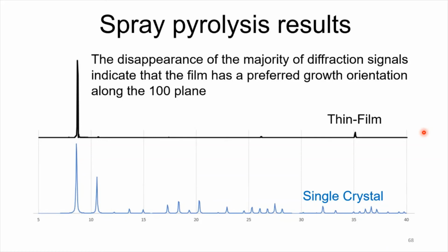As you can see, or what you cannot see, is the rest of the peaks. You can barely see some signals in there, and they are repeating signals. So we can go back to the single crystal structure and say, oh, it's growing into the 100 plane, because this peak here shows up, and this little one in here, and this little one in here. But the rest of them, they don't show up. That means that the film is really thin, and it's just growing into that 100 plane. So we have that preferred growth orientation that is, again, as I said, PXRD will show you right away.